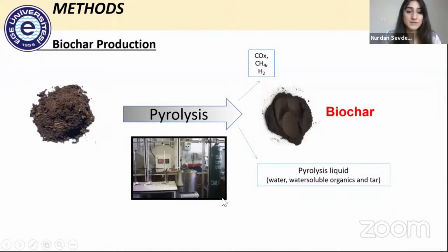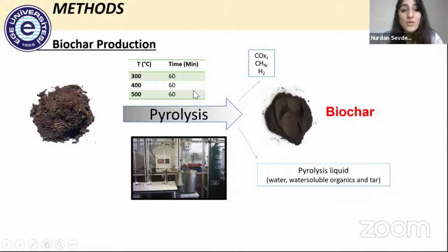In the biochar production experiment, dried poultry litter was pyrolyzed under a nitrogen stream at 3 different temperatures for 1 hour in a lab scale vertical fixed bed reactor. During pyrolysis, volatile products pass through traps where the liquids are collected, and non-condensable volatiles are released to the atmosphere. I'm not sure if you can see the trap here.